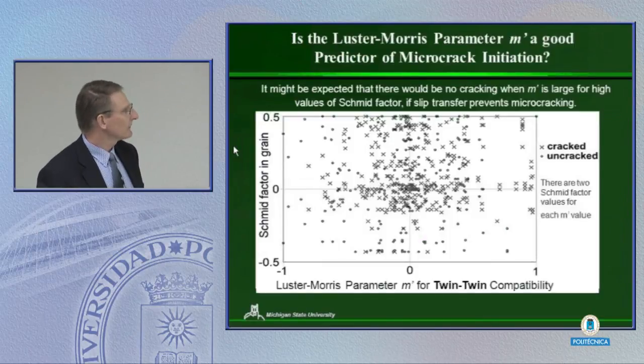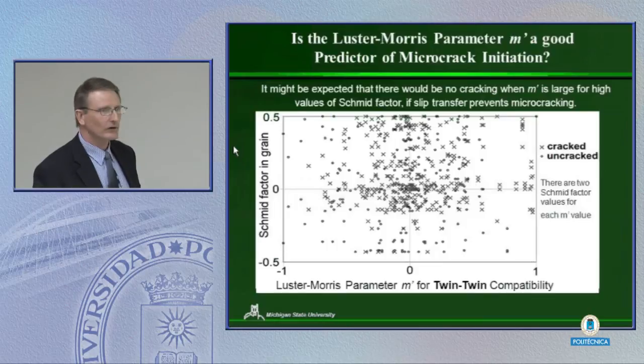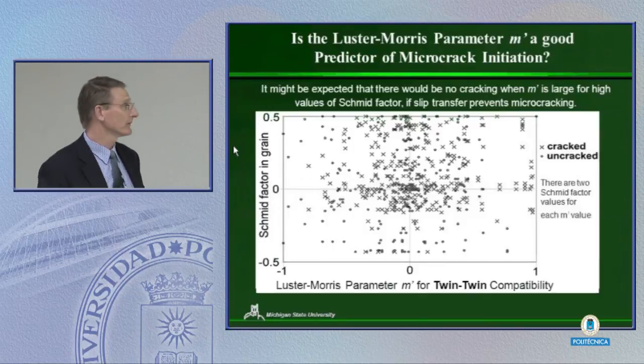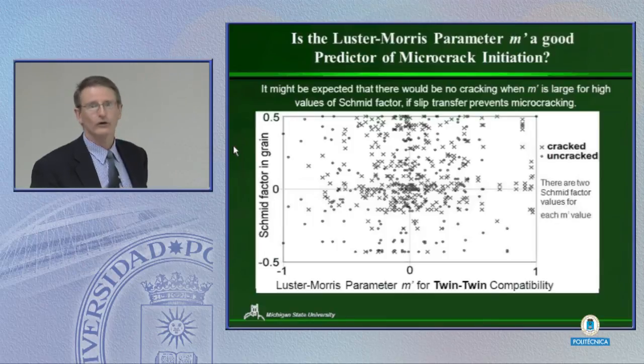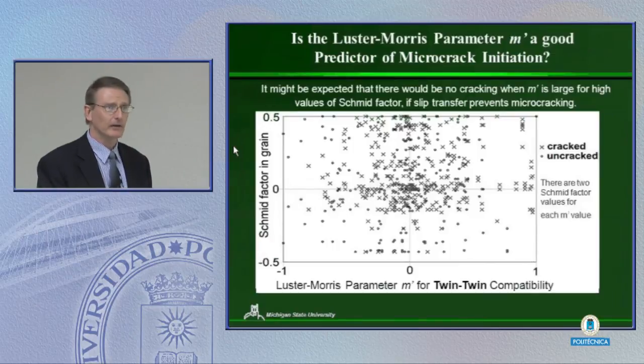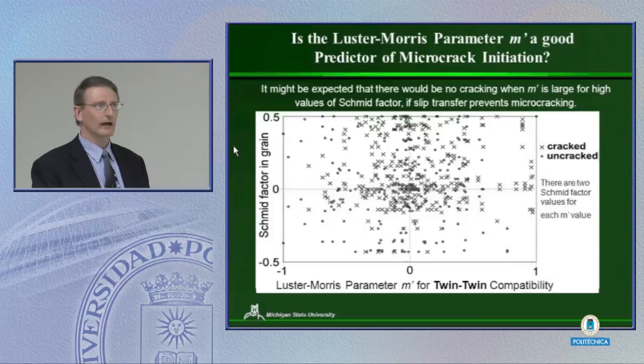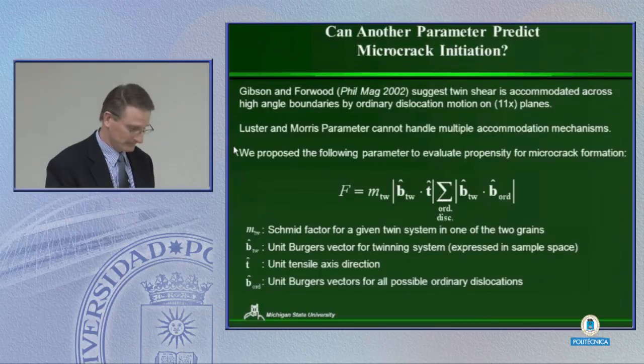And so we looked at that and we said, okay, what is the Schmid factor for a particular deformation twinning system? And what is this M prime? And this shows it for twin-twin compatibility, but we've looked at compatibility for different types of systems. And we plotted the cracked boundaries versus uncracked boundaries. And you can see that there is not a strong correlation. Okay? It says that even if you have good deformation compatibility, that does not predict whether or not you'll get fracture at the boundaries.